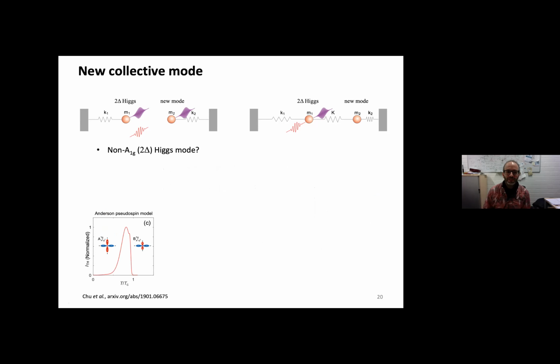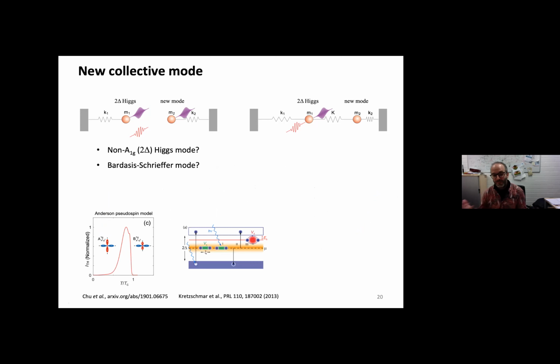The question is now, okay, what is this new mode in this system? One possibility is that this mode would be one of these non-A1g Higgs modes in the system. Other possibilities that were already discussed in the literature is that in some superconductors, you could have subdominant pairing channels in a system. So you could have other order parameters in the system, and they could, like an exciton, give in-gap states, the so-called Bardasis-Schrieffer modes, if they would be driven. For example, in pnictides, that would be a very famous example. However, in the cuprates, this mode is very, very unlikely.